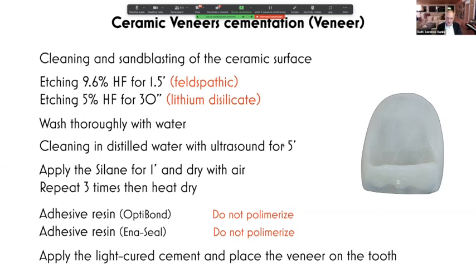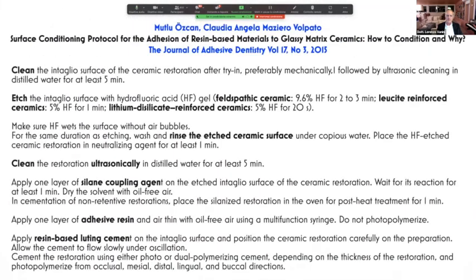This is important because you clean the surface very well and you eliminate all the residues left after the etching phase. You have to dry the surface very well, and then apply silane for 1 minute and dry with air. Repeat 3 times, and then dry. I use an air dryer. You can apply the adhesive resin, either of a traditional system, or I use Ena Seal. After this, you apply the cement inside and place the veneer on the tooth. This protocol follows the protocol published in the Journal of Adhesive Dentistry some years ago. It's the same protocol. You can check this work and you will find that I do the same.